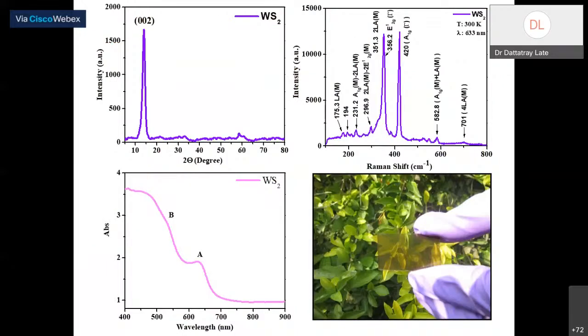I have done a lot of other characterization before I use them for some application. For example, I have done XRD. You can see XRD shows a (002) peak. So this indicates that I have grown a very good single crystalline WS2 layer on this particular SiO2 substrate. I have done Raman spectroscopy also. Raman spectroscopy also has these two particular peaks, which are known as E12g and A1g. In addition, it also has some other bands. And also the absorbance measurement and all these things. I can see the optical photograph, which shows that it is transparent in nature.